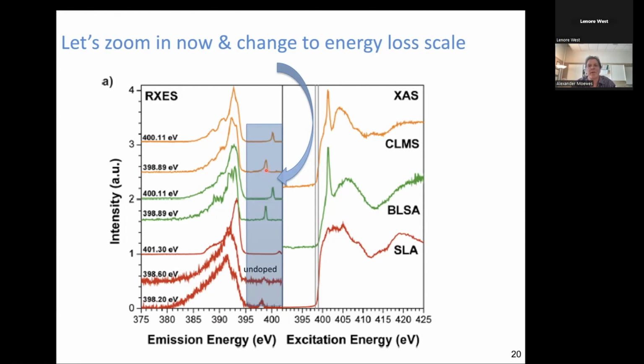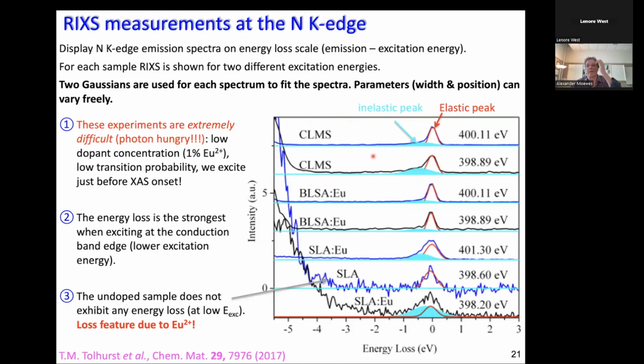So this is what I'm going to show on the next slide. Very different visual impression, just the same spectra shown here, just on a different energy scale, loss features, and scaled in height. And this is what's shown here on the right side. So the first thing to realize before you get upset about that, this looks like, as I always jokingly say, like a subatomic physics experiment, because it has very strong or large statistics. That is because these photon experiments are extremely photon hungry.